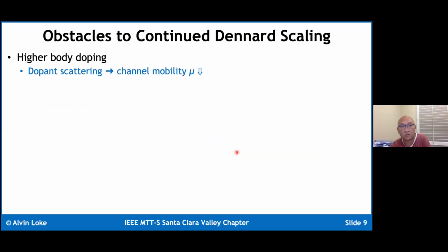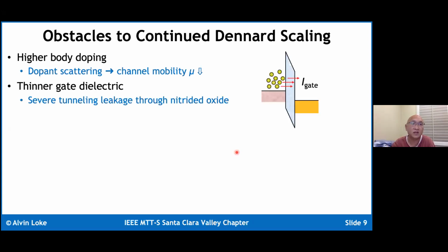Okay, so what are some of the obstacles to continuing this recipe? As I mentioned earlier, we're using higher body doping to make the depletion regions thinner. And so this naturally will increase dopant scattering. So ionized impurity dopant scattering is going to cause the channel mobility to go down, which is not good because you get less current. Okay. Also, the gate dielectric being thinner, you reach a point where basically electrons can just teleport from the gate to the channel, and this severe tunneling leakage results in severe gate leakage.